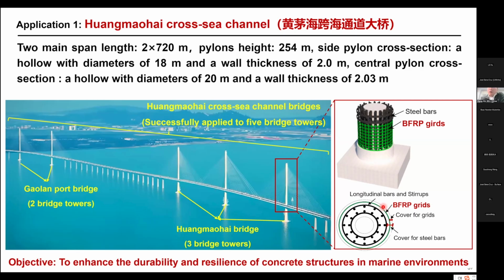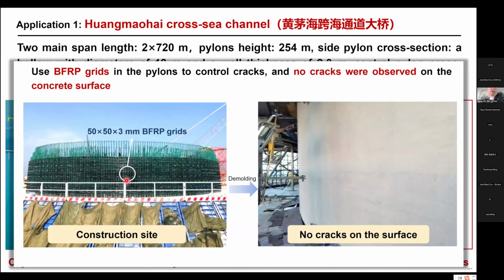So BFRP grids are a non-metal material, so they are free of corrosion. They can play a very important role here to control the cracking. Here is the construction site. See the black one, this is the BFRP grid. It is placed at the outside layer. The inner one, the green one, is the coated steel bars. After construction, almost no cracks could be observed.